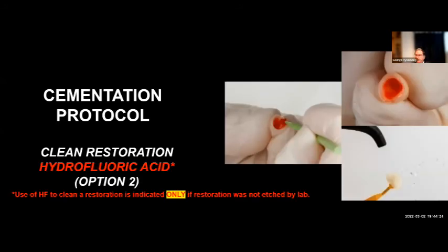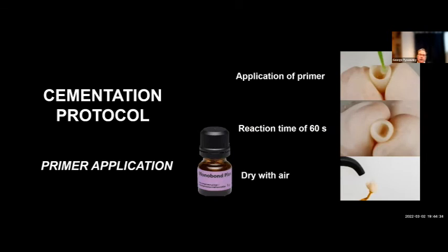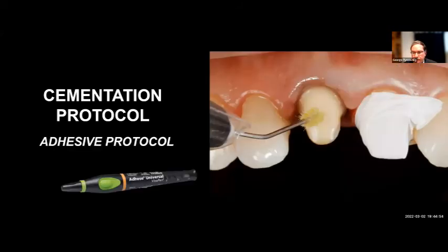We then hydrofluorically etch the restorations to make sure that they are adequate, with proper priming, so that we create this crystal structure in the glass ceramic material. And then we put a primer on there. These Monobond Plus and other multifaceted glass ceramic metal primers provide a very strong chemical link. It's like the old silanes, but much broader in chemistry application. So we put on the primers, we let it react 60 seconds, and we dry it with air to create this uniform bond with the material overall. So we've primed the restoration. On the tooth structure, we scrub the tooth with our universal adhesive. In our case, we're using Adhese Universal. We scrub it for about 15-20 seconds to create a micromechanical penetration and hybridization of the dentin.